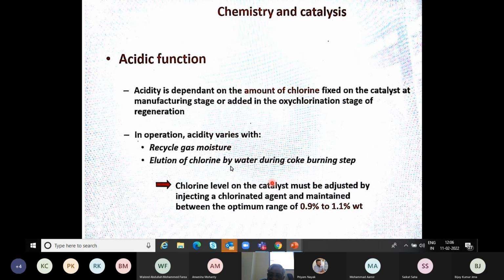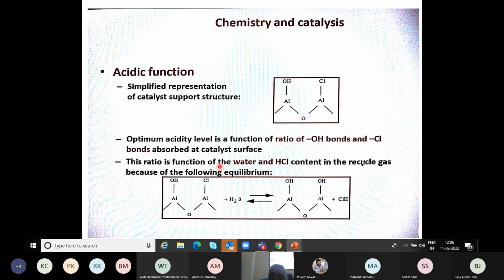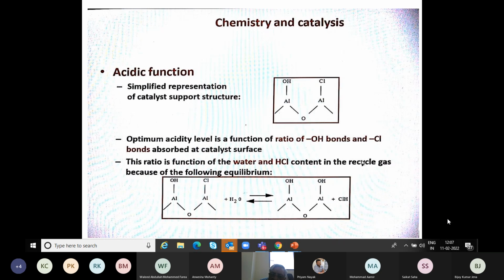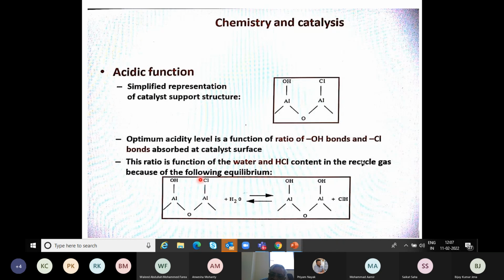The moisture, if it is present in the feed, results in removal of chlorine. It will be replaced by the OH group. Okay. So if this is my chlorinated alumina, and there is moisture coming along with the feed, then the moisture will replace the chlorine, and you get HCl formed, and you ultimately get aluminium hydroxide, which reduces the activity of the catalyst because there are no acid sites left anymore.